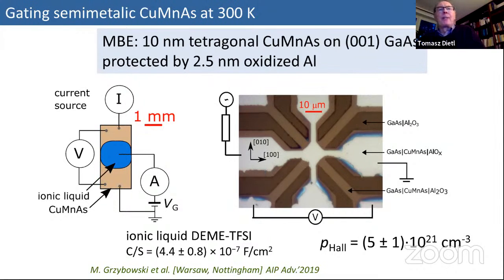Many of us are nowadays very much interested in antiferromagnetic spintronics, and you can ask the question about gating of this material. So I will show just very simple results concerning field effect in copper manganese arsenide, a very famous antiferromagnetic material used for spintronics. What Michał has done here is put ionic liquid on this thin layer of copper manganese arsenide, prepare a gate, and measure how the resistance of this material changes as a function of gate voltage.